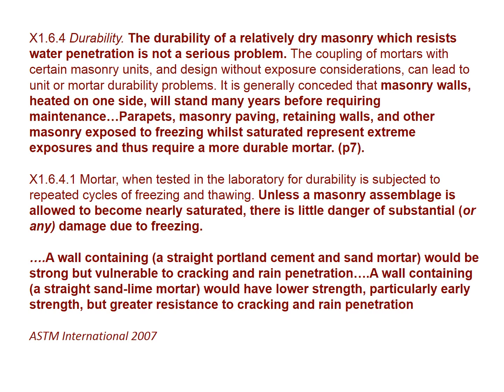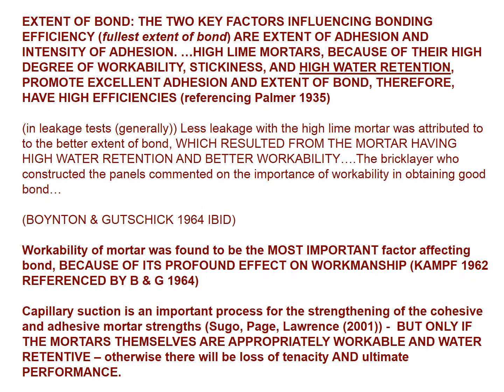Mortar, when tested in a laboratory for durability, is subjected to repeated cycles of freezing and thawing. Unless a masonry assemblage is allowed to become nearly saturated, there is little danger of substantial, or I would say of any, damage due to freezing. A wall containing a straight Portland cement and sand mortar would be strong but vulnerable to cracking and rain penetration. A wall containing a straight sand lime mortar would have lower strength, particularly early strength, but greater resistance to cracking and rain penetration. So extent of bond is very important.